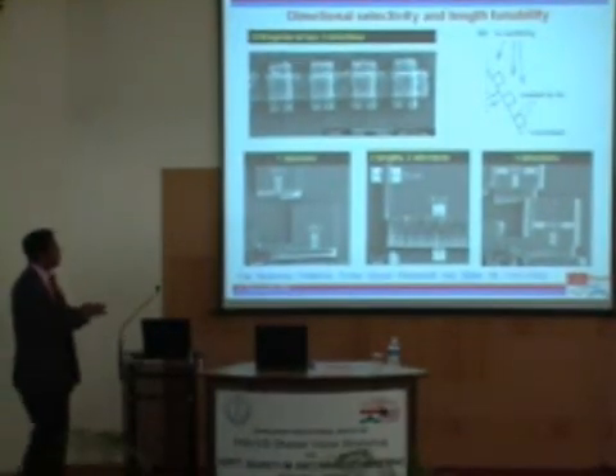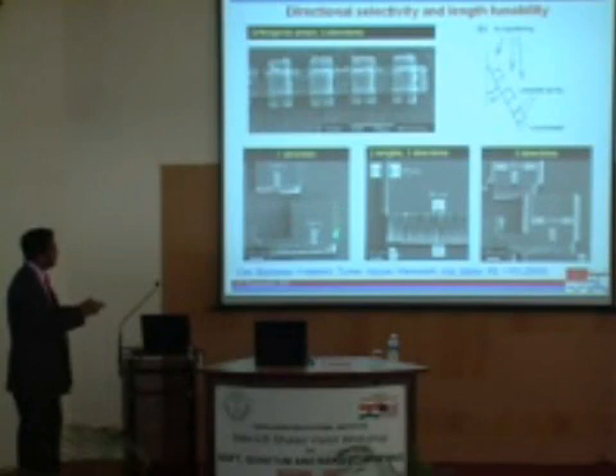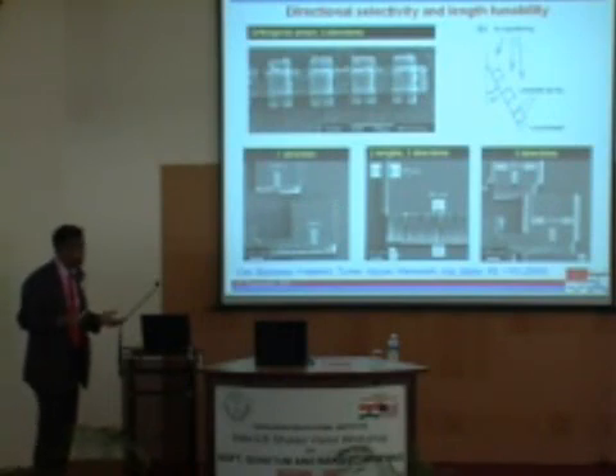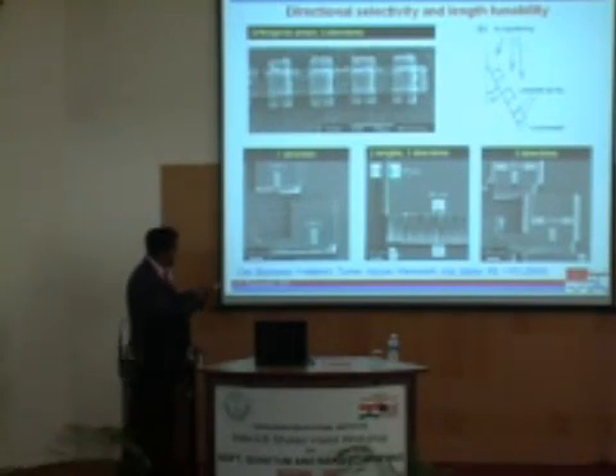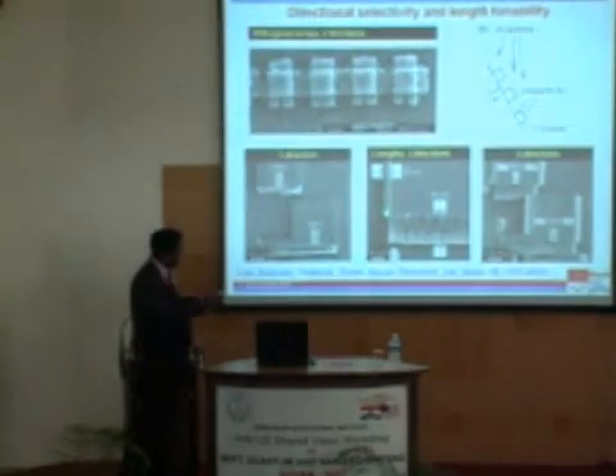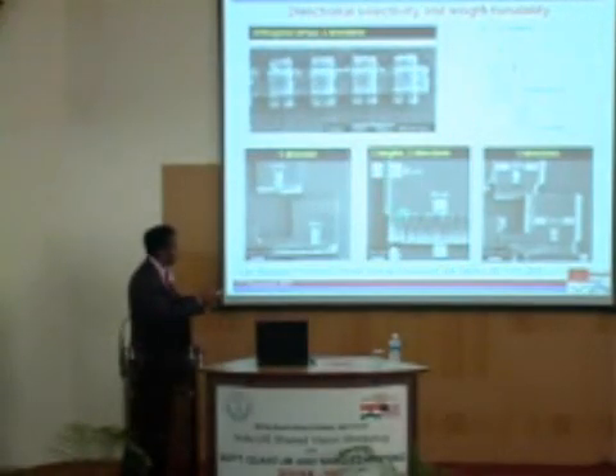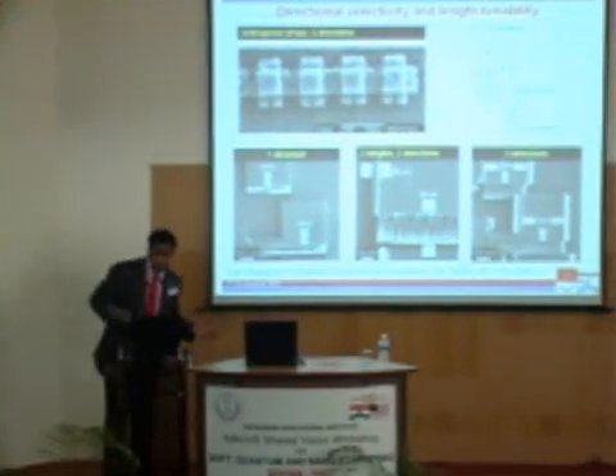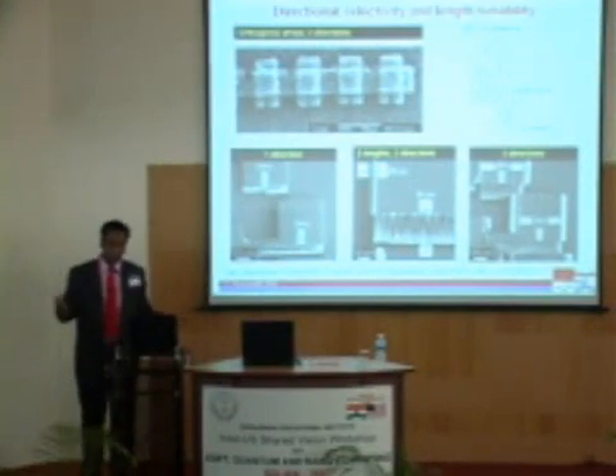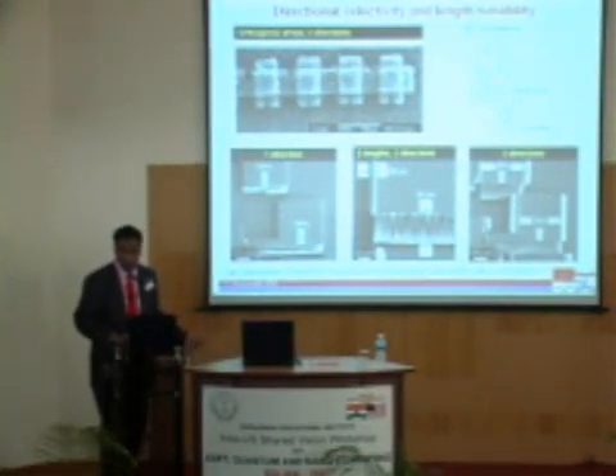Okay, and the idea is basically the gold in this particular case covers the rest of the areas, and you get no growth. Additionally, you can also notice that by putting different amounts of gold on different faces, you can also control the length. Because in a device structure, obviously you don't make devices with all the same length of the elements. You need different elements with precise control.